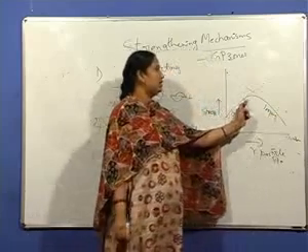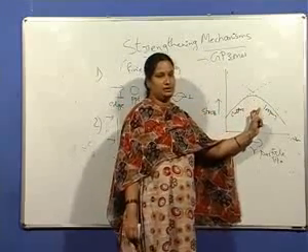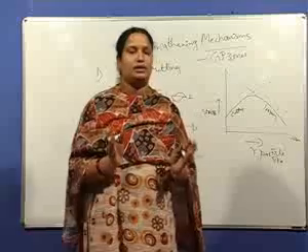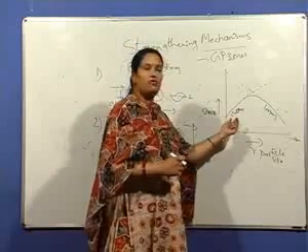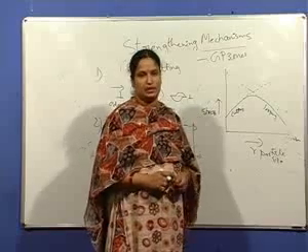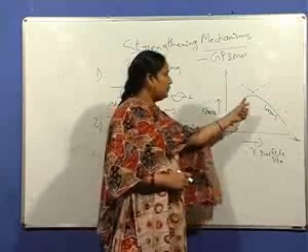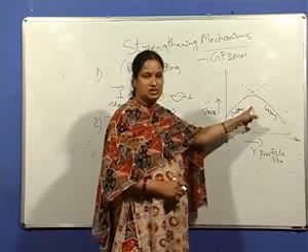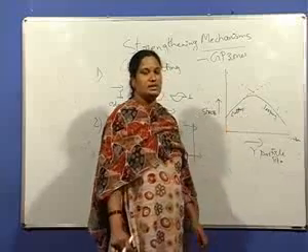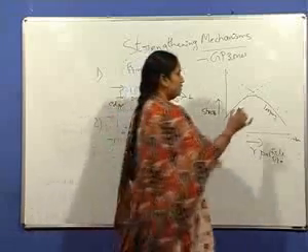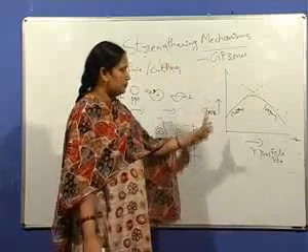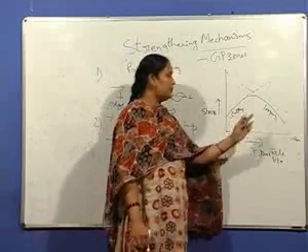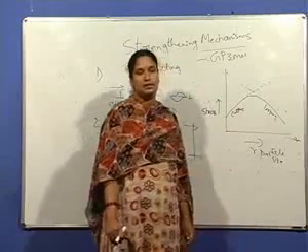Here you can see the curve does not have a sharp peak. Moreover, it is blunt. Why? Because normally any precipitation hardenable alloy consists of a mixture of both fine particles as well as coarse particles. So the peak hardness, or maximum strength, is due to both mechanisms, the cutting as well as the looping mechanism, at the peak. So this is one plot which shows the stress required with respect to the particle size for both mechanisms.